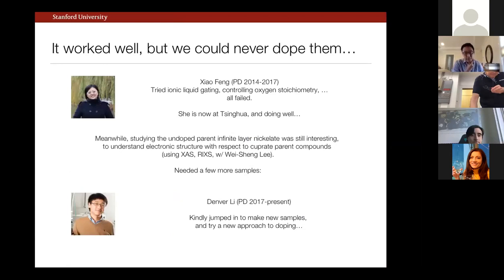And the basic reproduction of the synthesis worked well, but we could never dope them. So I thought I would tell, here and there, stories about how serendipity is such a key factor in all of this. A postdoc that worked with us, Xiao Feng, actually spent a good fraction of her effort over a number of years as a postdoc in our group. She was able to synthesize these parent compounds, but doping was never quite successful in the approaches we took at that time.